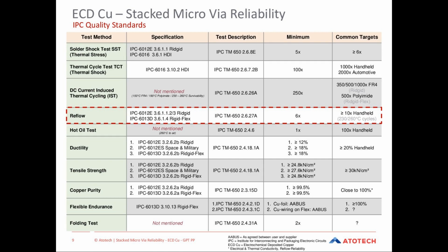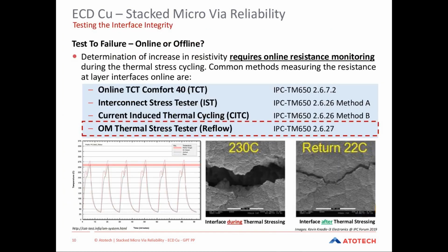And you see here an overview of the standard test procedures, which are well known and specified by IPC. And especially one method is more in the focus nowadays, and you can see it highlighted here by a rectangular red dotted box. This is the reflow simulation. This method is nowadays the most important and most helpful stress testing method to find out if your build-up is really reliable, if the interface integrity is good enough to survive thermal stress situations.